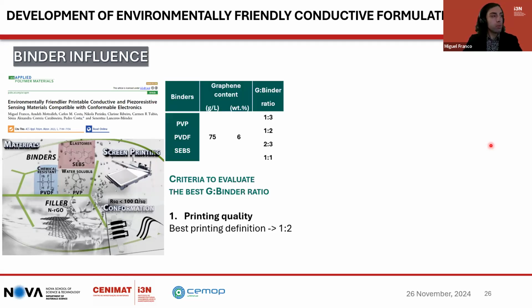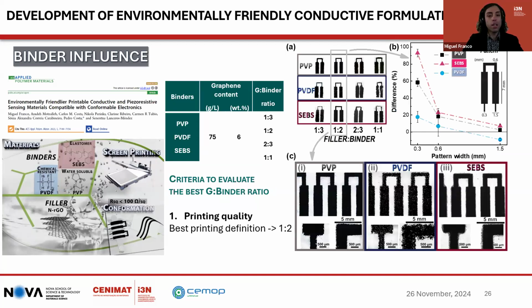It used nitrogen-doped graphene oxide, the same as previous, and the concentration was increased to 75 grams per liter. The graphene to binder ratio was changed in order to find an optimal one. To find the optimal graphene to binder ratio, three criteria were used. First, the criterion was printing quality. For that, an electrical pad was selected to evaluate the printing definition.